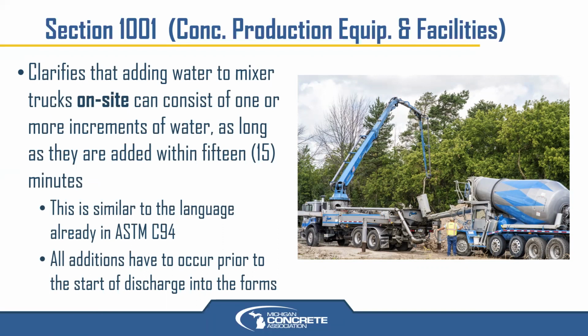And all those water additions do have to occur prior to the start of discharge into the forms. As it's always been, you can't pull up on site, add water to the mixer, mix it your 30 revolutions to mix that water in, start your discharge, and get 2 yards in and realize, hey, we want to add more water. I know it's done a lot of times on commercial and residential jobs, but on MDOT jobs, they allow one addition of water at the beginning and mix that water in, and if you start discharge into the forms, you're not allowed to add water after that.